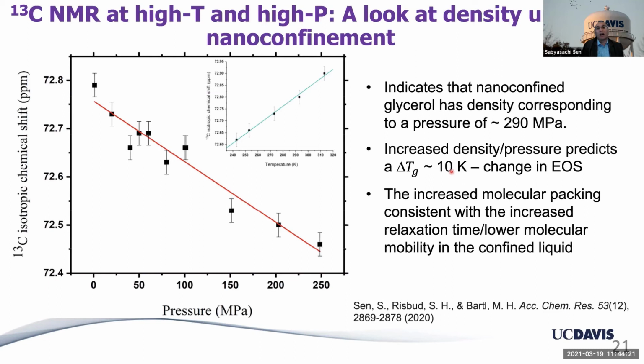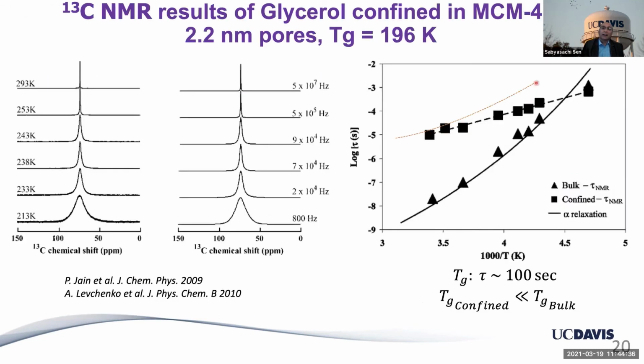So our finding that the glycerol density is quite different in the nanopore is consistent with all this, and says that there is indeed a change in the equation of state. So it may not be surprising that the alpha relaxation process is fundamentally different, and the same process that controls alpha relaxation becomes a beta relaxation in the nano-confined state.